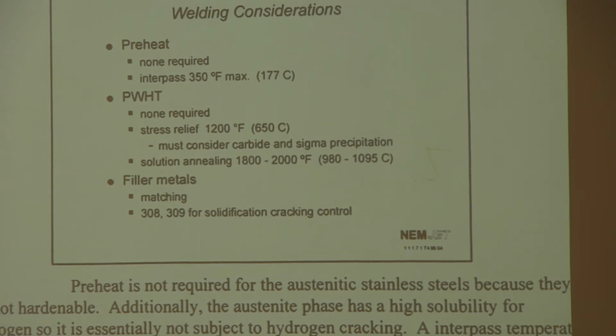Filler metals that are typically used in welding of austenitic stainless steels are either matching, or 308 and 309 are very common for welding on 304, for example, because of the solidification microstructure that you end up with that has some ferrite in it, which is what we're going to talk about in a minute.